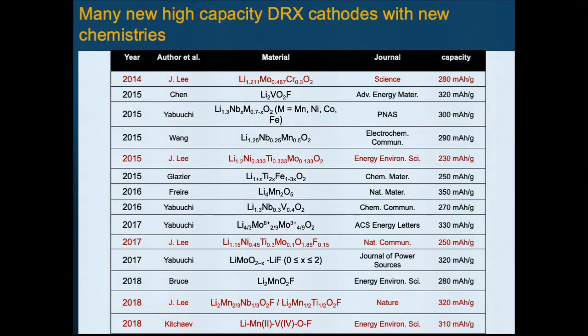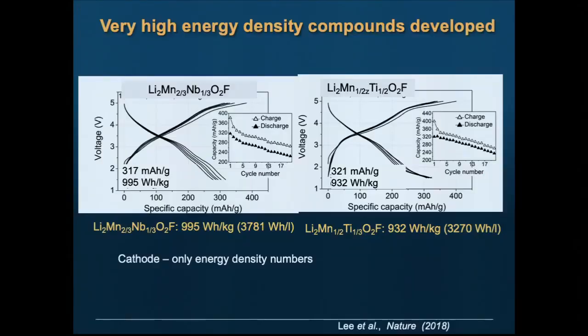Since then, lots of people have appeared on the scene, made all kinds of materials with very different chemistries. And if you look at this, this has a lot of chemistry that is not present in today's lithium-ion materials. We use molybdenum, chromium, vanadium, niobium, titanium. So in some sense, we've really unlocked the periodic table here by doing this.